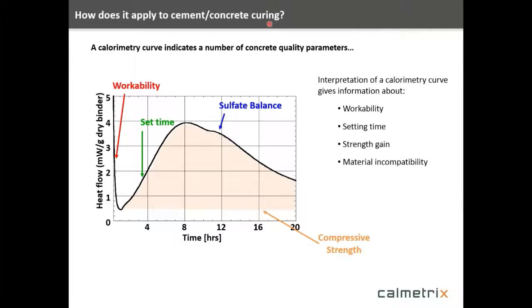So how does this apply to cement and concrete? Well, the curve that we get provides us a number of things that we can look at in terms of the parameters associated with the curing of cement and concrete. So here's your typical curve. Again, we're plotting here in this case heat flow in watts, milliwatts in this case, as a function of time. So there are many things we can glean from this basic curve. Of course, the initial reaction is an indication this is where the concrete is workable. You enter into the dormant phase.